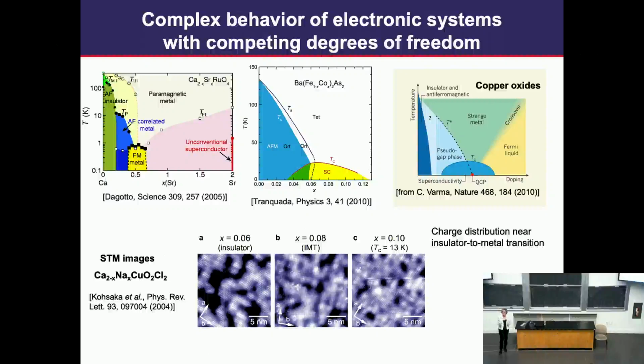And as you get into the superconducting phase, okay, these regions are connected, but it's still inhomogeneous. So you can imagine that there can be many possible arrangements, configurations of these nanoscopic regions that would have similar energy, and you would expect then to have a Coulomb glass. And indeed, some years ago, we did look at one of the cuprates, and we found evidence for charge glassiness in addition to spin glass behavior, but I will not talk about that today. Let me move on. So we want to keep things simple.